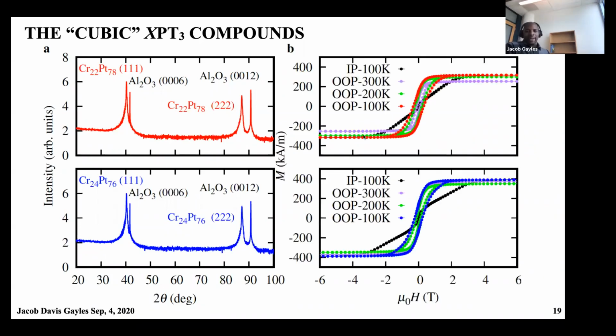And we measured the magnetism for this, and we found that it has this hysteresis loop. So the black shows the in-plane magnetization, and the color shows the out-of-plane magnetization at different temperatures. It also shows this hysteresis loop and this hard magnetic phase going from the in-plane to out-of-plane direction, which is quite different for a cubic system.